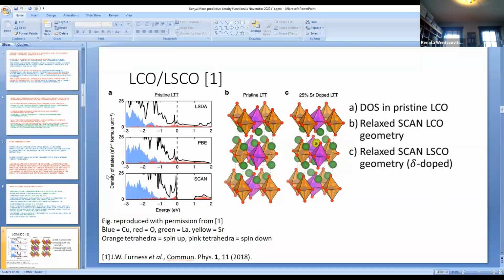The gap closes, and the material becomes a metal, and that's where it is able to superconduct. So we don't actually capture the superconductivity because that's too delicate an effect, but we get a very good description of the underlying material in which the superconductivity is found.